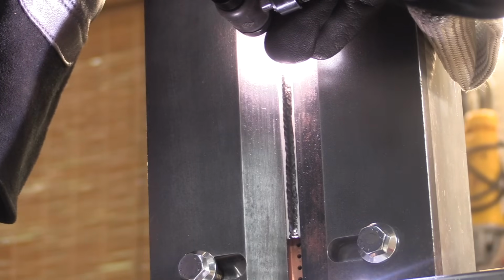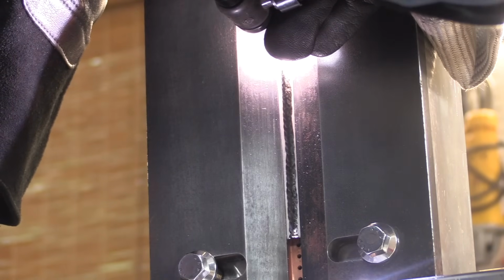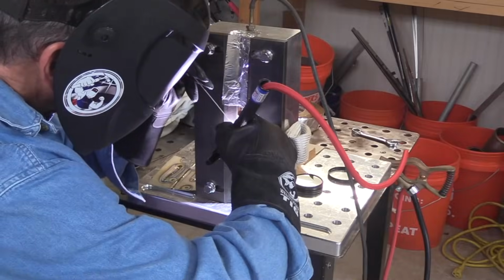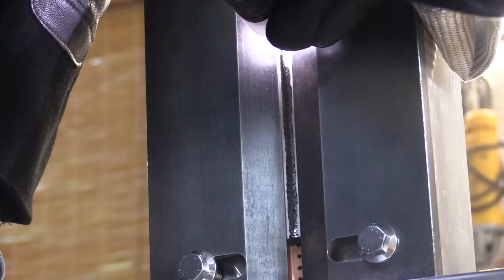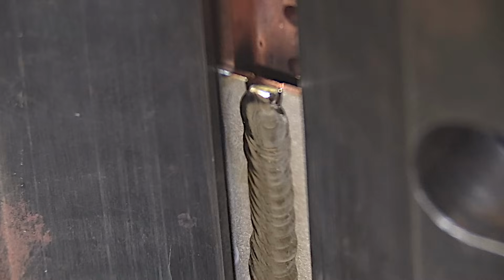The fourth video was the same test but 3G, vertical uphill. The thing about vertical uphill titanium, the rod is sticky, so you've got to aim for the center of the puddle, the hot part of the puddle, and you've got to figure out a nice way to prop and be comfortable and slide along evenly. Also with some really tight clear arc shots on how not to melt that end away but still get full penetration all the way to the very end and maintain good gas shielding for a silver weld.